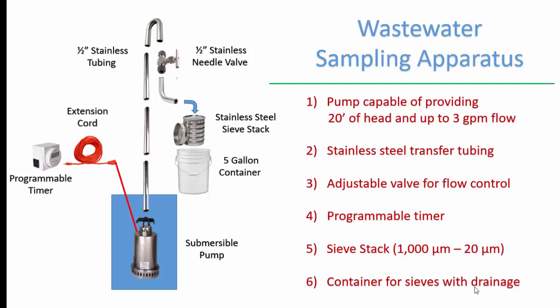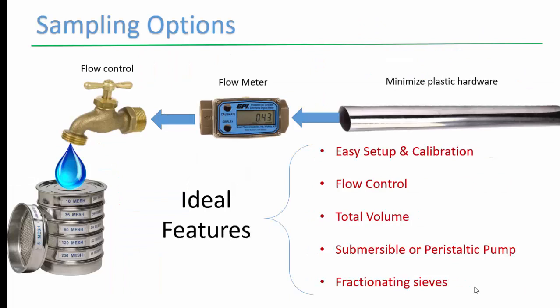Sieve stacks you can get in various porosity diameters, and then some type of collection sieve. Here it's showing a plastic bucket, but we took a regular aluminum bucket and drilled holes in the bottom that contained all the sieves in it. One other key feature that you should consider is an inline flow meter. An inline flow meter will help you dial in the flow control of the volume going to the sieves. That'll avoid overburdening them, but also a flow controller that is also a totalizer and records total volume processed. That's very handy. And so the ideal features would be something that's easy to set up and calibrate, something that allows flow control, something that records total volume. You can use peristaltic or submersible pumps, and fractionating sieves.